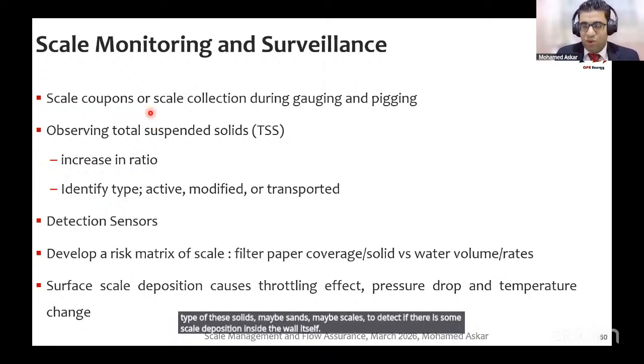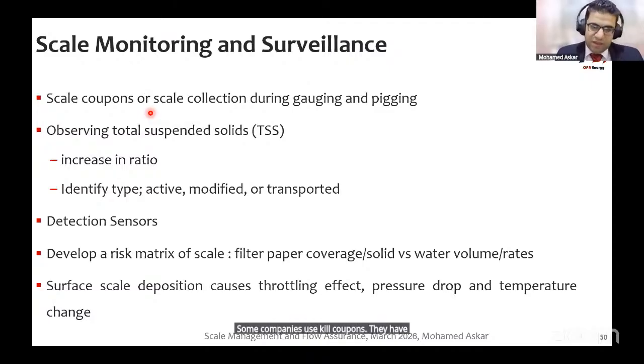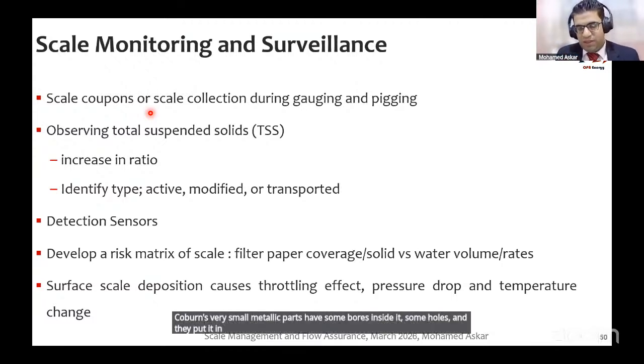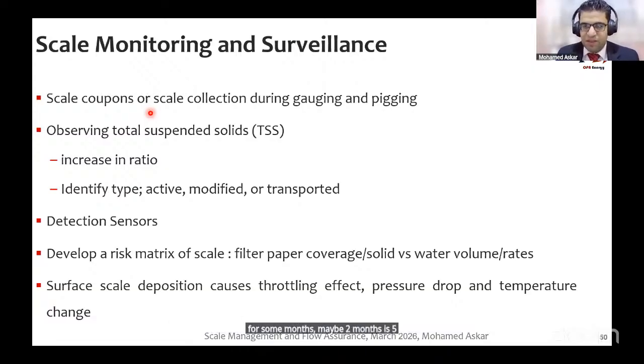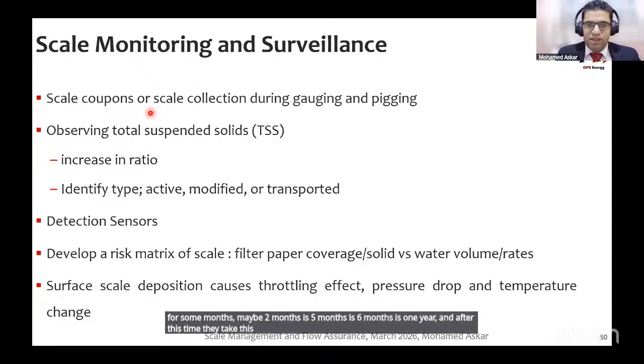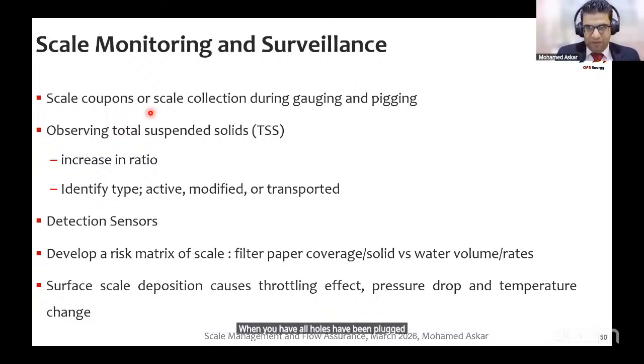Some companies use scale coupons. They have some coupons, very small metallic parts, with some pores inside, some holes, and they put them in the flow line for some months, maybe 2 months, 5 months, 6 months, 1 year. And after this time, they take this coupon and see how many holes have been plugged. When all the holes have been plugged, it means you have a high tendency of scale.